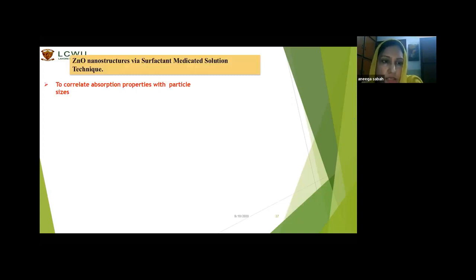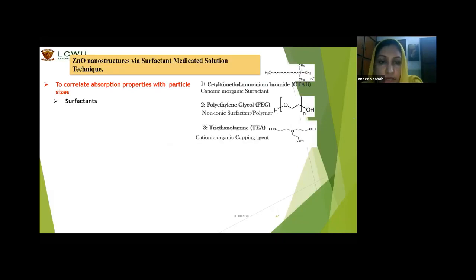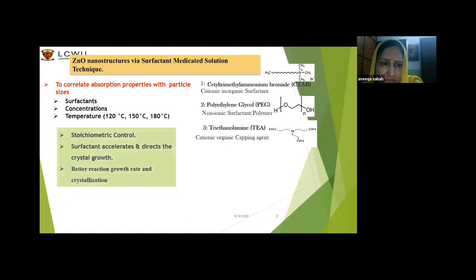The other thing we have done is zinc oxide nanostructure via surfactant mediated solution. We used different kinds of polymers acting as surfactants, and by applying different conditions, stoichiometric control, the surfactant accelerator directs the crystal growth, giving better reaction growth rate and crystallization. We obtained this to prepare zinc oxide nanostructure using these surfactants at different temperatures.